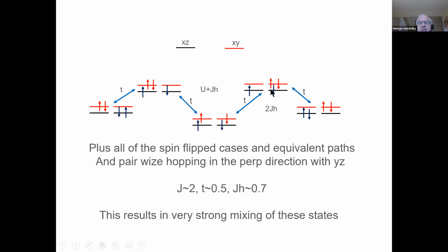So now you have a spin of a half on each one of them. The energy cost is U plus J Hund, putting the energy of this thing at 0. And the hopping integral is T. Then you can go ahead and hop this black electron from the XZ orbital to the left, giving it to the XZ on the left. Then you get this picture here. This is a spin 0 state, okay? And this costs you twice Hund's rule to do this. And you have many of these possibilities. You can go this way, but you can also flip spins around, making singlets or triplets.